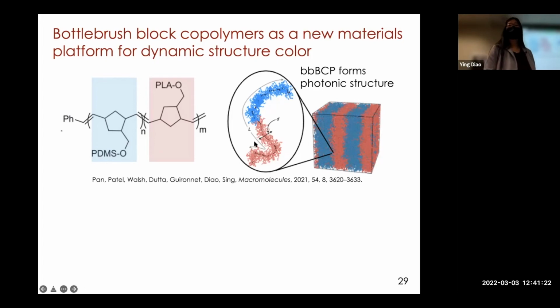And the reason why this is interesting is because if you don't graft the side chains, the polymers are actually very, very flexible. So they fold and densely pack, so that when they assemble into these lamellar layers, the spacings are actually very small, tens of nanometers. But then when you graft these arms, the polymer becomes much more rigid. So the spacing goes into the visible range, about 100 to 200 nanometers. And that creates vivid structural color for this material.